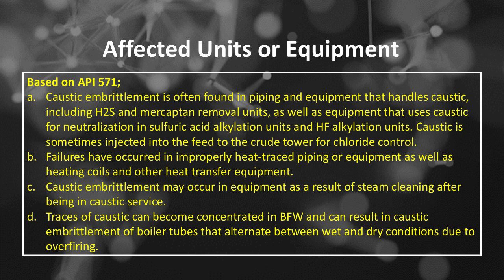Number B, failures have occurred in improperly heat-traced piping or equipment, as well as heating coils and other heat transfer equipment. Number C, caustic embrittlement may occur in equipment as a result of steam cleaning after being in caustic service. Number D, traces of caustic can become concentrated in BFW and can result in caustic embrittlement of boiler tubes that alternate between wet and dry conditions due to overfiring.